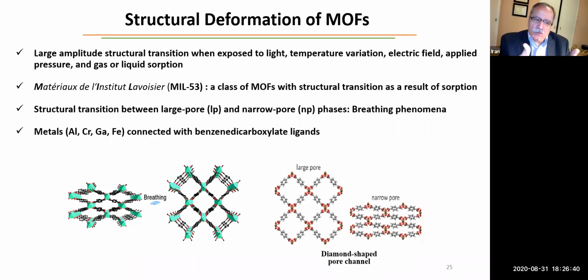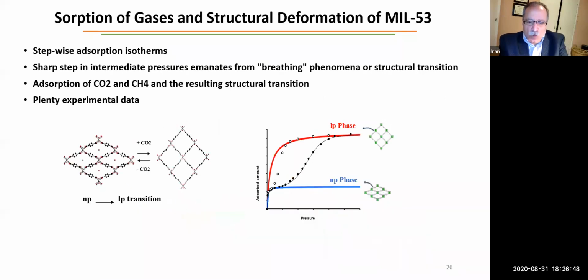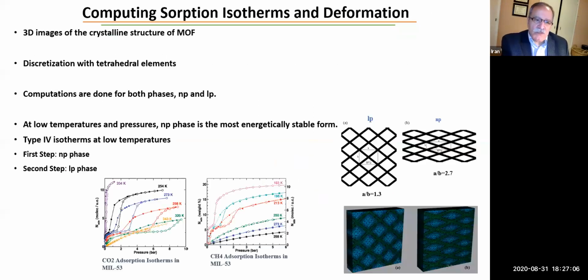So your chest goes up and down. This is the breathing phenomenon, where you have narrow pores and large pores, and this is actually very difficult to model. The adsorption isotherm looks like this. On the top right, you see the large pore phase, with that type of configuration. And on the bottom left, you see the narrow pore phase, where the material takes that type of configuration, and we want to model this.